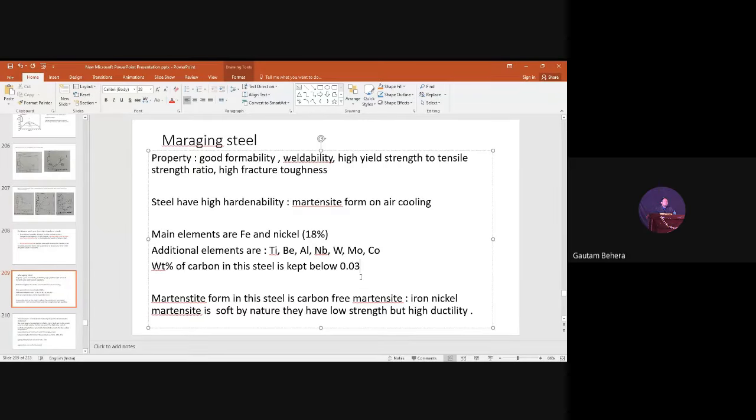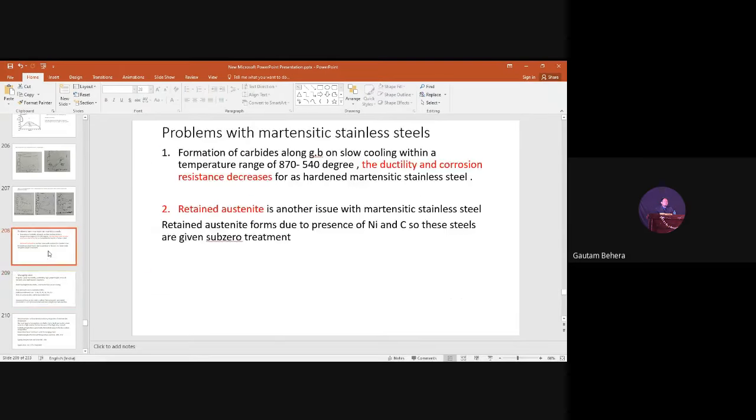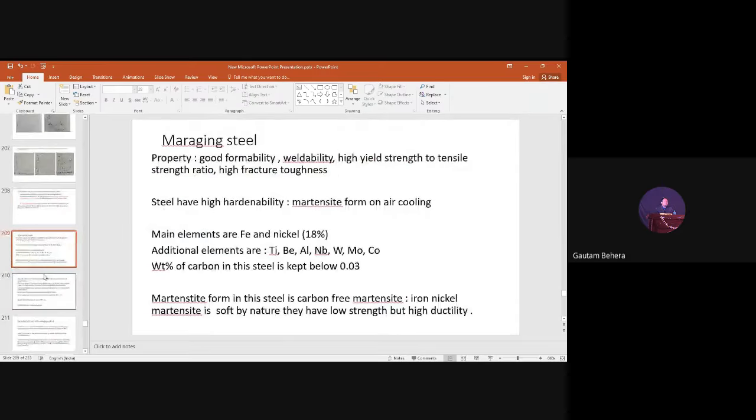During martensitic transformation, the C axis wants to shrink, but due to the presence of this carbon at the center of the edge of the BCT, the shrinkage will be very minimum. So obviously strength will be very high. That is called tetragonality, if you remember. We discussed it in previous lectures.